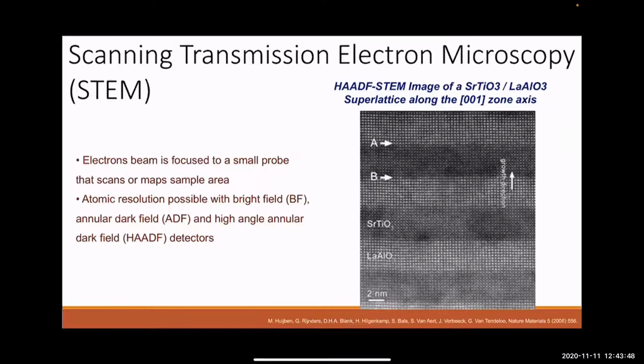There are a number of advantages and disadvantages between using a TEM in conventional TEM mode versus STEM mode. And there are some cases where it's better to use STEM. STEM is better, for example, for thicker samples and for reducing damage, because you're not on any one spot of the sample for very long, whereas with bright field TEM, the beam is continuously shining. And while we consider it non-damaging, that's not actual reality. That electron has a bit of energy and can actually damage your sample, especially prominent with softer materials like polymers or biological materials.